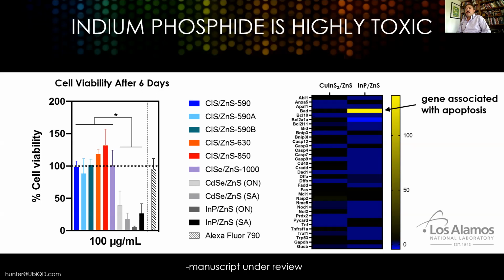that the cell viability at a high concentration, roughly 100 micrograms per milliliter, after 6 days was essentially 100% for all of the forms of our quantum dots, with a variety of peak emissions and ligands, even when we had selenium, which we sometimes alloy in to extend the emission wavelength. Whereas with cadmium-based materials, between roughly 25 and 50% of the cells remained. So roughly 75% or so of the cells were dead. And then indium phosphide was even worse. Depending on the supplier, we saw almost complete cell death with indium phosphide quantum dots under the same apples to apples study. We also looked at gene expression, and we found that the indium phosphide quantum dots had upregulated genes associated with apoptosis, which is related to cell death as well.